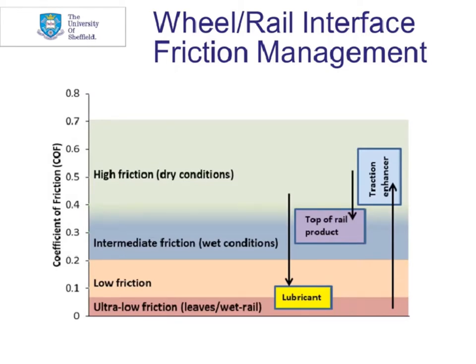So a big area I've worked on since starting work on the WheelRail interface has been management of the friction within the contact. This is important for quite a number of reasons. Obviously, controlling the friction helps to a certain extent to control the damage within the interface. So you would want a low friction solution in the flange gauge corner contact as you go around a curve.